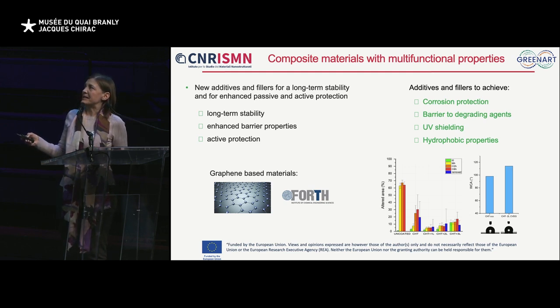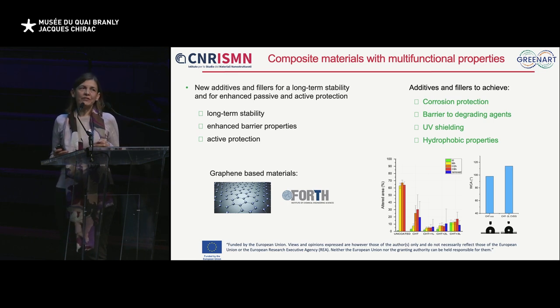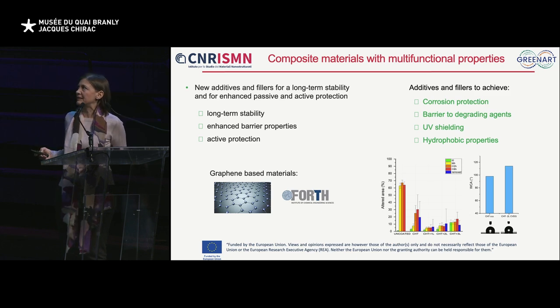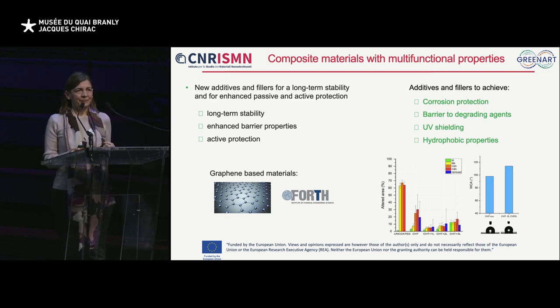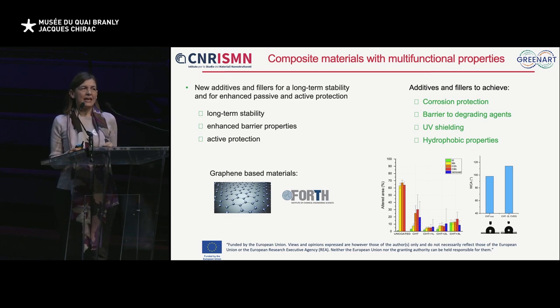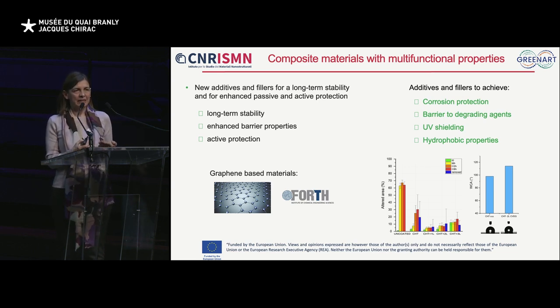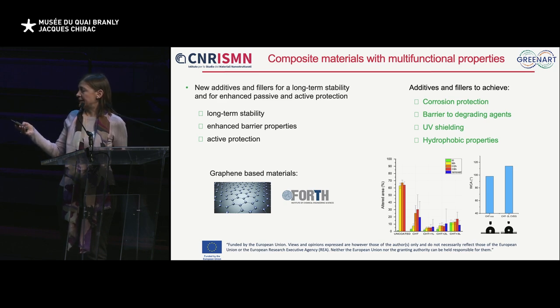You can see the percentage of altered area after accelerated corrosion treatment. And we can see that the altered area can be reduced by applying 1, 2, and 3 layers of graphene on the surface of the biopolymer coatings. In addition, we also observe that the contact angle after application of the graphene layer increases, so we can promote and enhance the hydrophobic properties, so by increasing the barrier properties, and this justifies the lower percentage of altered area.